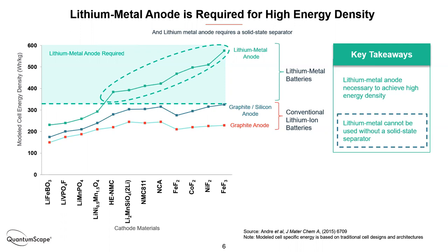all of that host material, and you can break free of that limitation and see as much as a 2x improvement in energy density. And it doesn't matter so much which cathode you choose, you're always going to do better with lithium metal. It's considered to be the holy grail in the industry. And Quantumscape certainly is not the first to think of this. It's been a goal for 40 or more years, in fact. But one of the keys is that it's very difficult to make work. Because of lithium's properties, it turns out that you need a solid state separator to really get it to function without reacting, forming dendrites, and failing. So we'll talk more about that in a second.